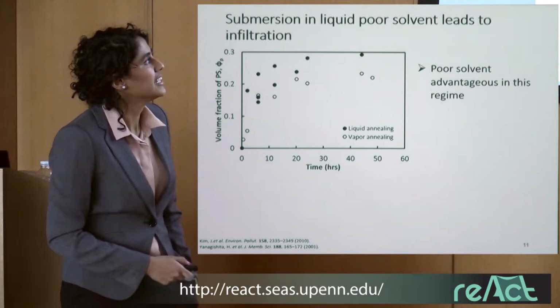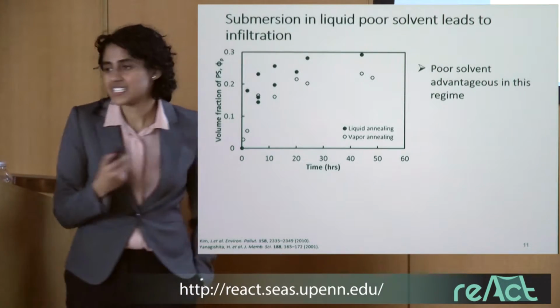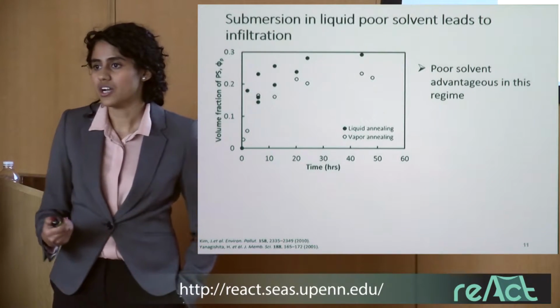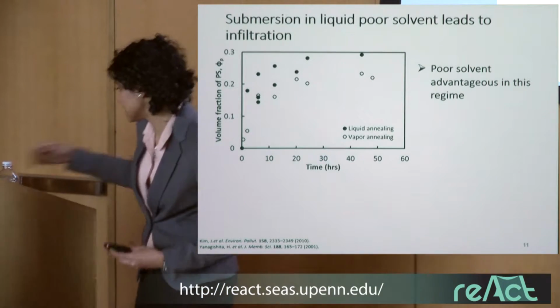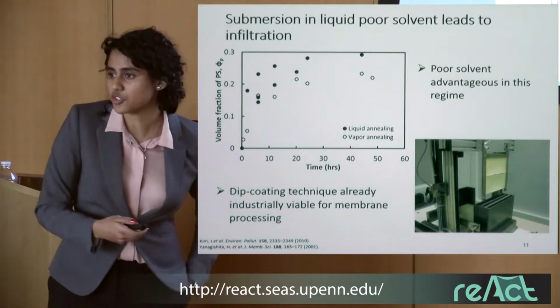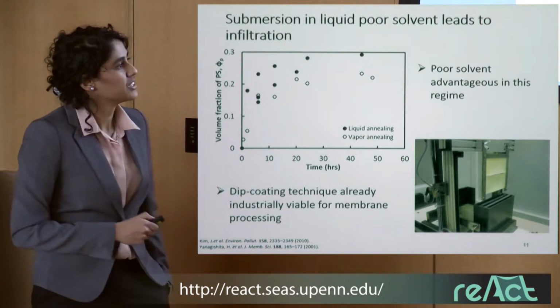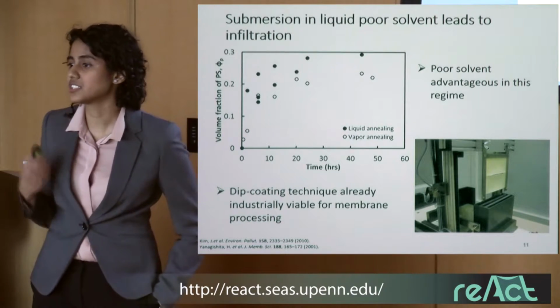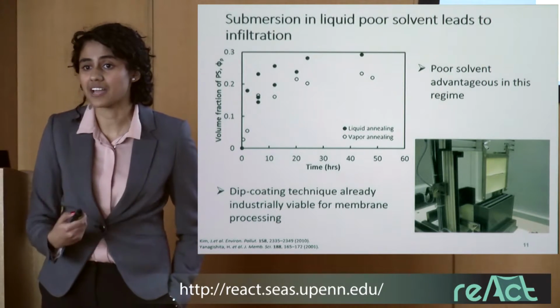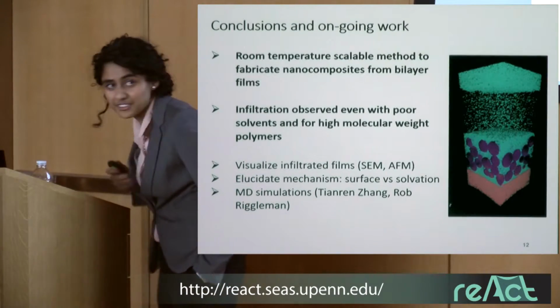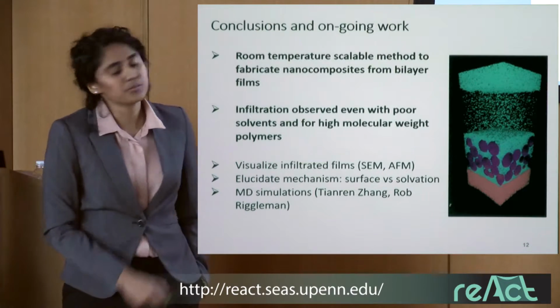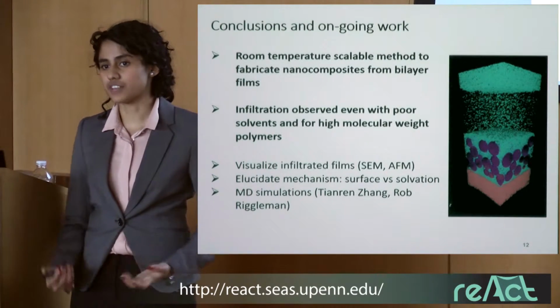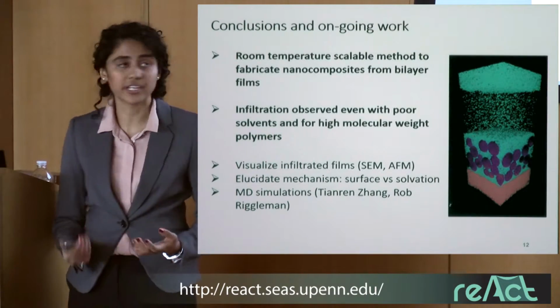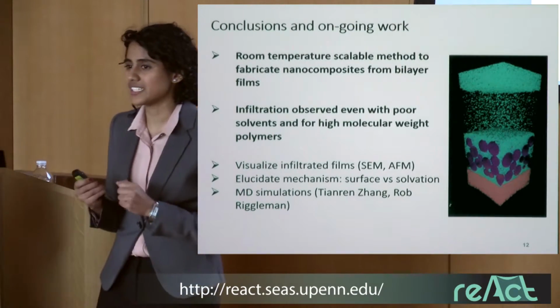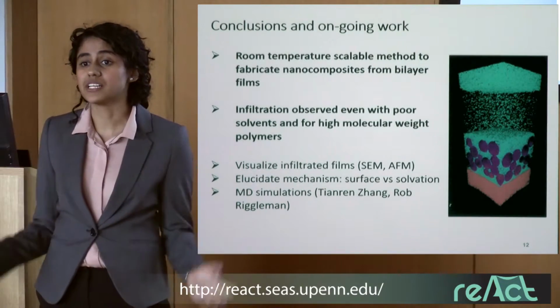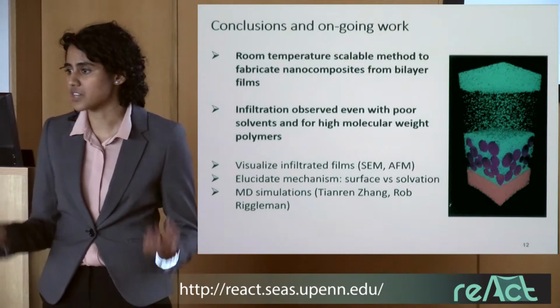And you can imagine that this is very advantageous going back to the scalability issue of making these nanocomposite membranes, because there already exist industrial techniques for dip coating, especially for membrane applications. So this seems like a more industrially viable route for making these nanocomposites with very high filler fraction. So to summarize, I've been able to develop a room temperature scalable method that can create these high filler fraction nanocomposites potentially for membrane separation applications. And this infiltration appears to be quite robust in that I can use different molecular weights and I can use a range of solvent quality to drive this phenomena.